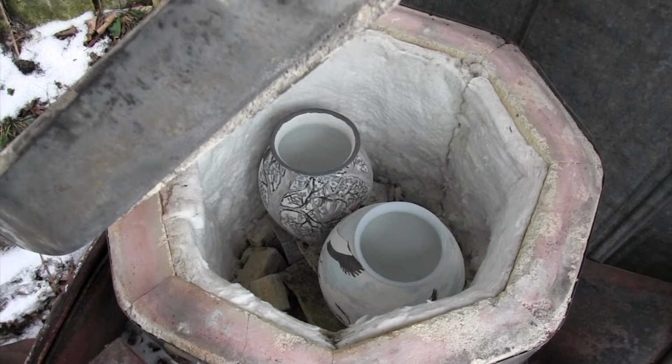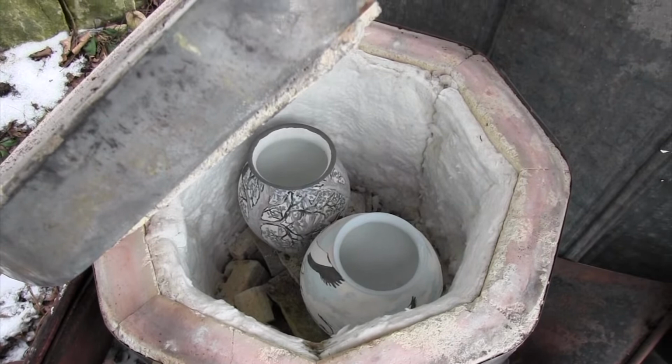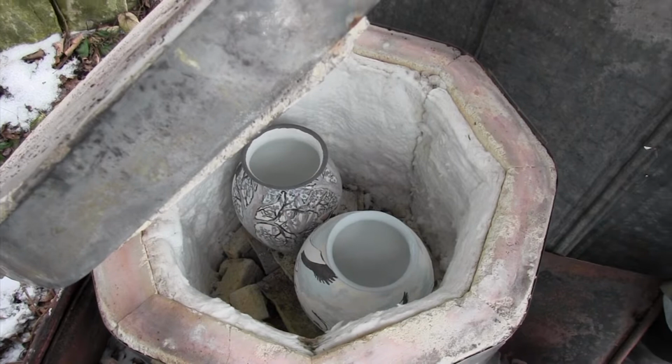You watch, because as glaze heats up, it goes from a powder that's on there now, starts to melt, and then it starts bubbling. The bubbles pop and it goes to like a moon surface with these craters. But then the next step is it flows together like glass. And when you watch it, it'll be glowing red when it's at that stage. When those bubbles and craters disappear and it becomes glossy, then you've got to reach in